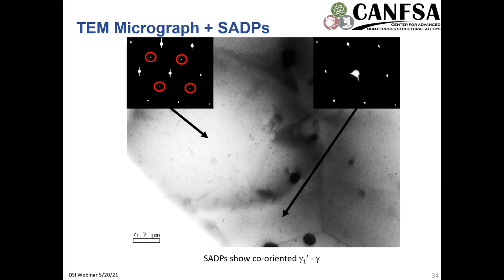So to be able to show a little bit better in terms of distinguishing between the gamma and gamma prime that the EBSD was not capable of, we have a TEM micrograph here with selected area diffraction patterns for these two corresponding regions. And we have the primary gamma prime here, and then this is an incoherent grain boundary following along through here, right there. And this is a co-oriented gamma-gamma prime boundary. And we have the SAD patterns with superlattice reflections within the gamma prime here, showing this is indeed the ordered structure, as well as the absence of the superlattice reflections within the same orientation of the SAD pattern, showing that these are co-oriented with each other. And this is likely occurring as a result of the dissolution of the primary gamma prime to form the stable gamma that is occurring at this prior region that was previously primary gamma prime.